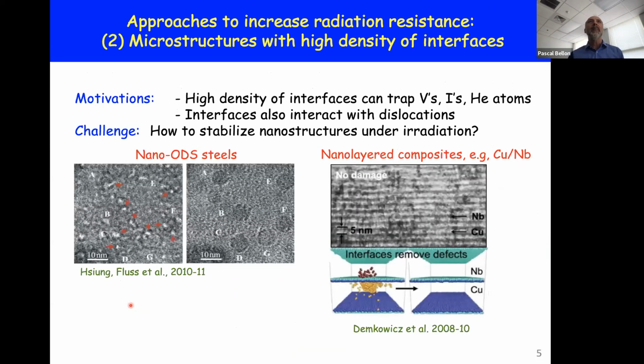So the second strategy, instead of relying on recombination, is to rely on interfaces, with the idea that interfaces will trap vacancies, interstitials, and helium atoms, and promote recombination or the annihilation of those point defects. I illustrate here two implementations of this strategy. One where one would introduce a high number density of very small oxide precipitates in a steel. These are known as nano-ODS steels, and the interface between the oxide nanoprecipitates and the matrix seems to be a very effective sink for point defects, and so these are attractive materials.